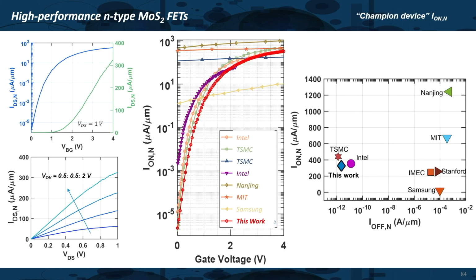And then when you compare it, this is a plot I wanted to draw your attention to. Many devices show very high on-state current, but they cannot turn off at Vg equal to 0, because the place you want to be in this plot is the upper left-hand corner, right, because you need to have both high on current and large on/off ratio, or low off current at Vg equal to 0. And that is something that has not been really achieved. Okay, you can get high on current, but you cannot turn off the device. So threshold engineering becomes extremely important. But you can see that we have been able to get to the corner where TSMC and Intel are. I mean, TSMC and Intel are still a little bit better than us. Okay, and our champion device gets up to almost 300 microamps per micrometer current.